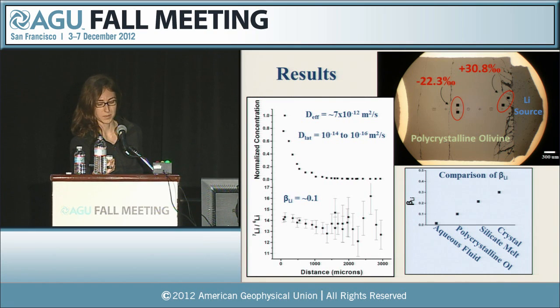So this just shows some of the results that we have so far. On the left here, you see normalized concentration as a function of distance. So this is 0, this is 3,000 microns. You can see that the concentration decreases in error function style. And this gives us a value of about 7 times 10 to the negative 12 meters squared per second. So this would be the effective diffusivity, and what I mean by effective diffusivity is the combined effects of the lithium diffusing through the crystal lattice as well as the grain boundaries.